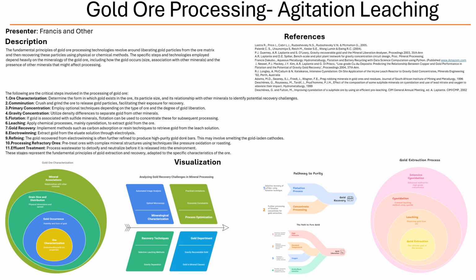It is, and the notes point out an interesting phenomenon that can happen in CIP circuits. What's that? Well, they say that some additional gold can actually be recovered in the adsorption section due to desorption of gold cyanide complexes from the ore particles themselves. Wait, what? So the gold can actually come off the ore and then reabsorb onto the carbon. Yeah, that's right. It's like the carbon is acting as a scavenger, pulling out even more gold than was initially leached. That's pretty cool. Okay, so we've got the gold loaded onto the carbon. Now how do we get it off?